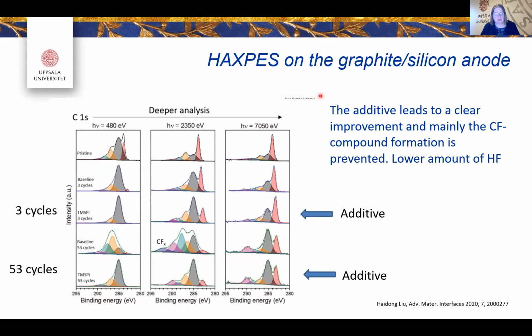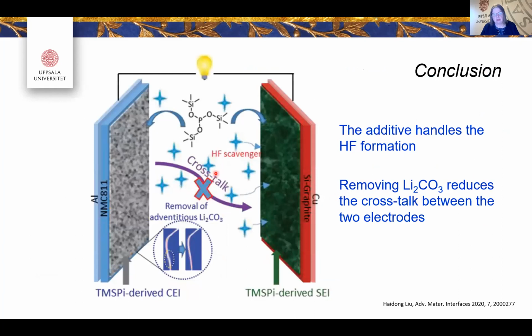And if you look at the graphite silicon electrode, you can also see that the additive leads to clear improvement, and mainly the CF compound formation is prevented. Is this peak here? You can see here at the baseline, and you see it's not here after 53 cycles when you have the additive. So you have a lower amount of HF. It's actually not only good for the cathode, it's also good for the anode. So what you can say is that this additive actually prevents some kind of crosstalk because it's removing this lithium carbonate from the positive electrode, and it also scavenges the HF, which is good for the anode. So it has several good properties in this case.